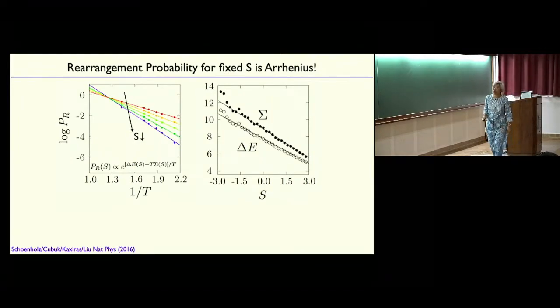More precisely, if I look at the probability of rearranging for particles of a given softness as a function of 1 over temperature, for high softness what you see is a straight line. Log of the probability versus 1 over temperature is Arrhenius, or Boltzmann, dependence. That means there's a well-defined energy barrier for particles of a given softness. And this is where the physics comes in. This quantity is so useful because it's a good enough predictor that we see Arrhenius dependence of the probability of rearranging for particles of a given softness. For soft particles, I see something like this: a lower energy barrier, lower entropy barrier.